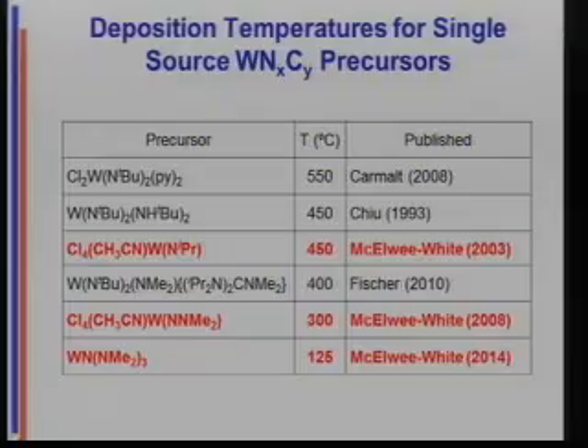So to sum up the CVD part, this is what we were able to do by doing some mechanistic chemistry, right? Before we got really started on this, everybody was stuck at 400 degrees. And that's because all of these precursors had intact amido ligands. There's N-t-butyl, N-t-butyl, here's our N-isopropyl, N-t-butyl, and the rate determining step is cleavage of that C-N bond. And so as soon as you step away from that as a design feature, then here's the hydrazido, that drops to 300, and get rid of that bond entirely, and now depositing at 125. And so that's what happens when mechanistic chemists get involved in these kinds of projects.